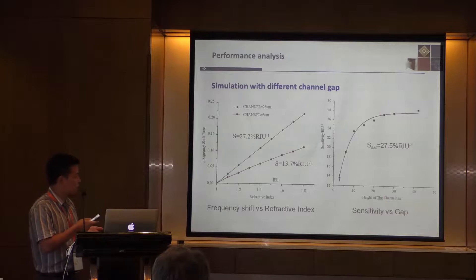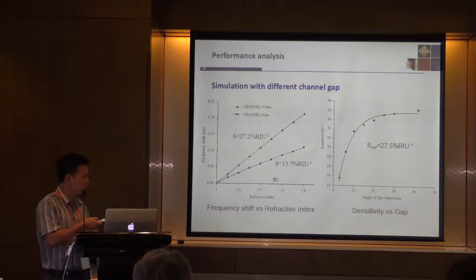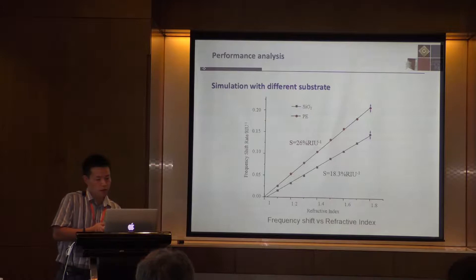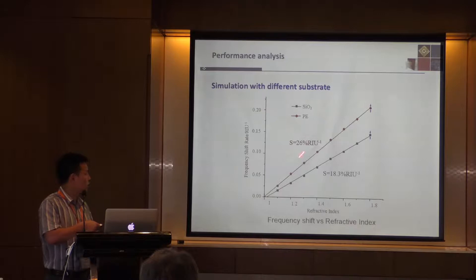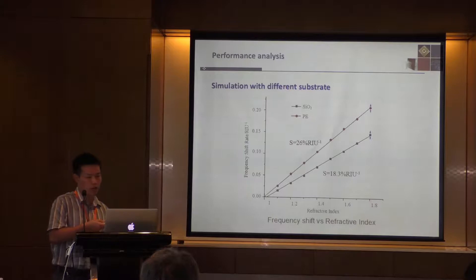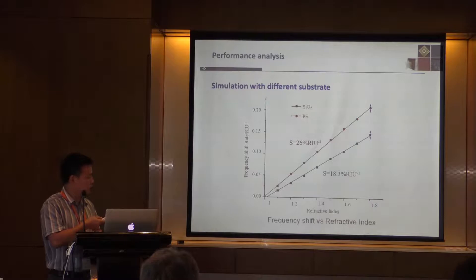So with the liquid samples, if the thickness of the samples is above 25 micrometers, the sensitivity is almost the same. This is the limitation. After that, we also have done some simulation work with different substrates. We found that with the PE substrate, it's better, because PE is transparent in the terahertz band. We have done lots of work with other substrates and we think PE is the much better one.